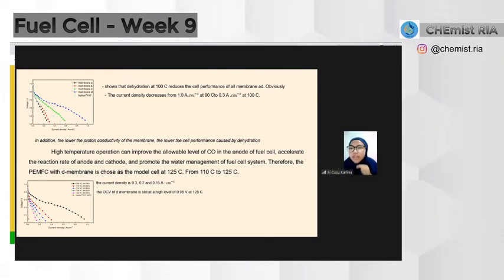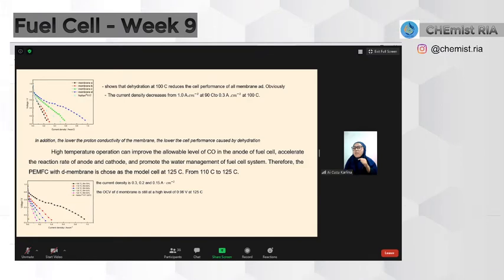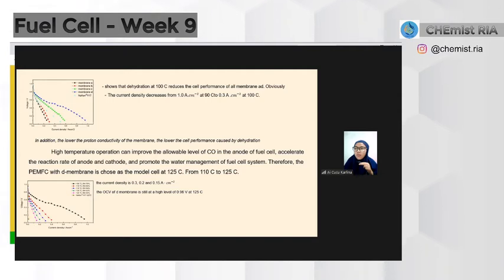We can see in the figure that dehydration at 100 degrees Celsius reduces the cell performance of all membranes. Obviously, the negative effect of dehydration on cell performance outweighs the positive effect of the accelerated reaction rate due to the increase of temperature at 100 degrees Celsius. The current density decreased from 1.0 at 90 degrees Celsius to 0.3 at 100 degrees Celsius. In addition, the lower the proton conductivity of the membrane, the lower the cell performance caused by dehydration.